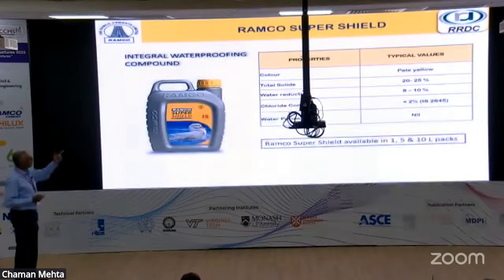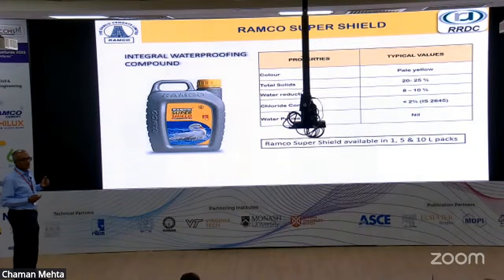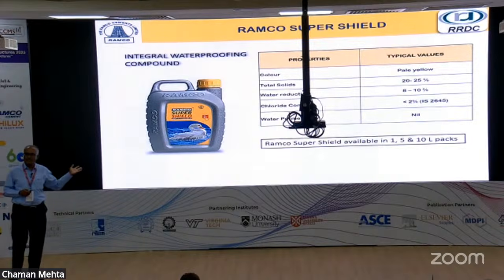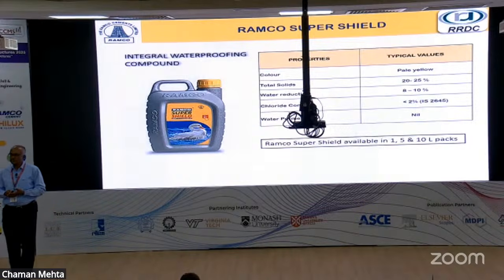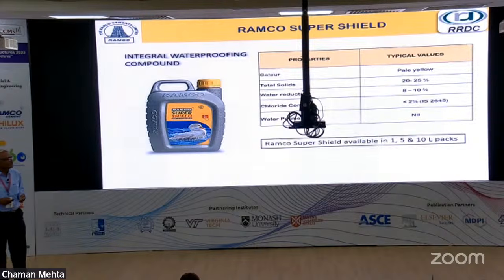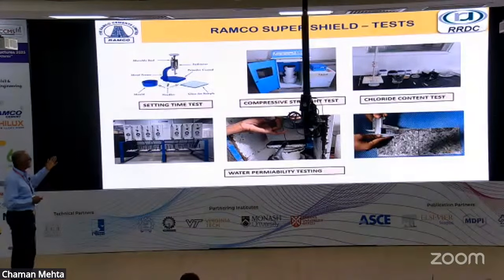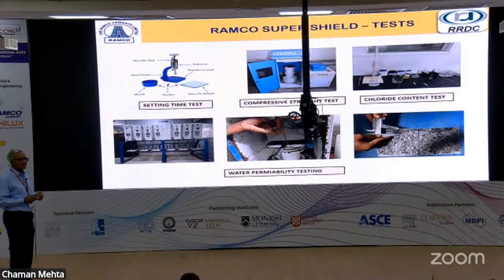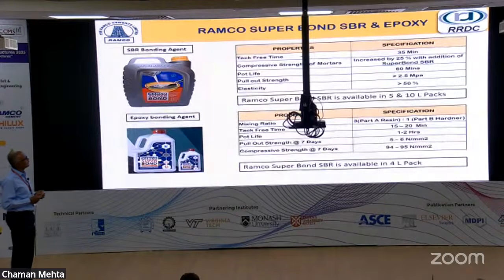Super shield, of course, is the integral waterproofing compound which is added to concrete. The basic purpose is to reduce the water cement ratio. It is basically used in the retail segment where they are not able to reduce the water cement ratio by using the conventional methods. So it is effective in reducing the water cement ratio to such an extent that your workability is not compromised and you get a higher strength, and thereby the durability is also enhanced. So these are the kind of tests that we do. The water permeability test is one test that we do as far as the integral waterproofing compound is concerned.